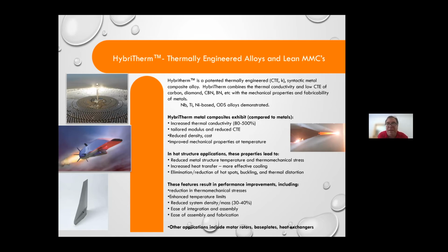They do offer advantages in hot structures, being able to tailor and move thermal energy around and tailor the CTEs and the residual thermal stresses and the thermal stresses due to extreme temperature gradients. This leads to elimination or reduction of hot spots, buckling, thermal distortion, and in attachments and putting dissimilar materials together basically help bridge the differing expansions, temperatures, and thermal stresses. And these can reduce significantly the density and mass.